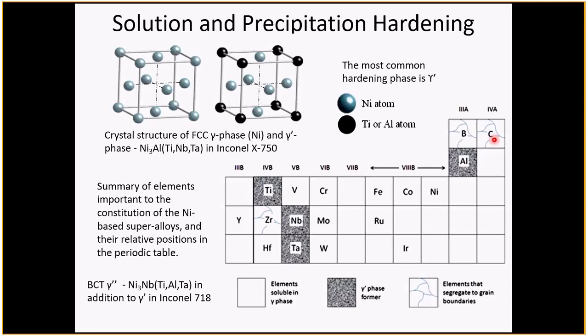These are the M23C6 typically, and this formation creates a depleted zone of chromium, and chromium is in the alloys to give it good corrosion resistance. So you've got to be careful if you heat treat nickel alloys to a certain extent. The chrome creates carbides but is depleted at the boundaries, and then these boundaries are subject to intergranular attack either by acids or just simply by corrosion.